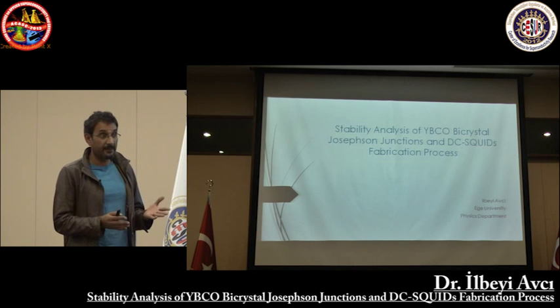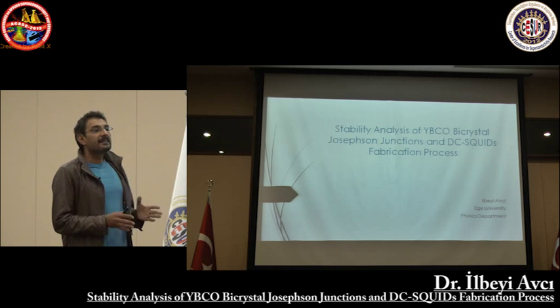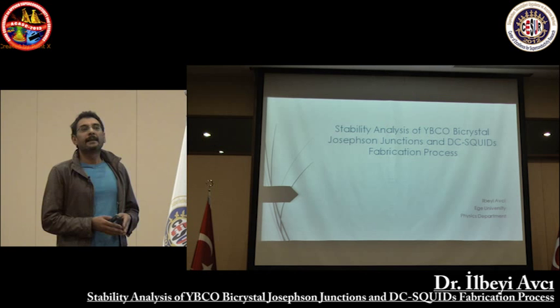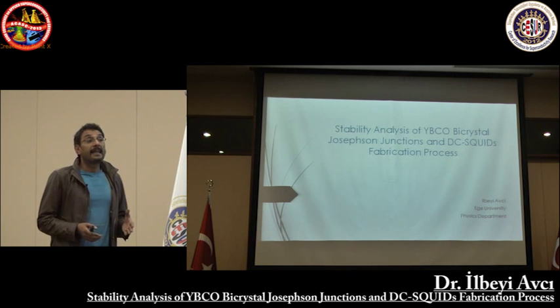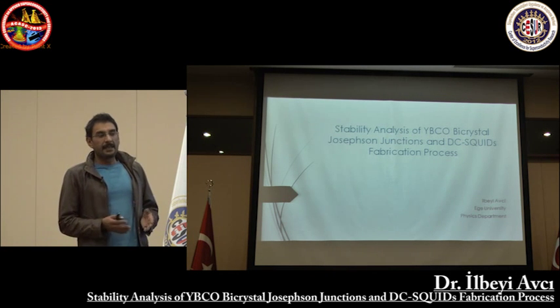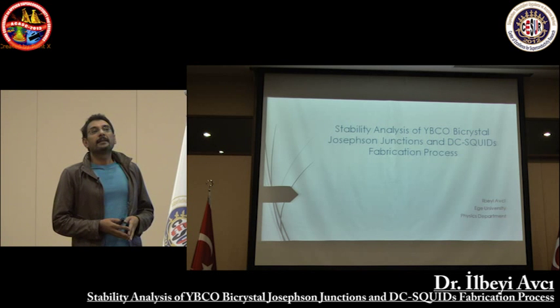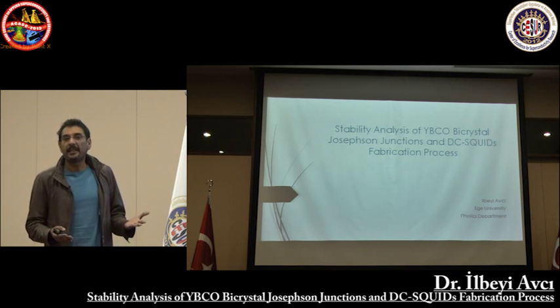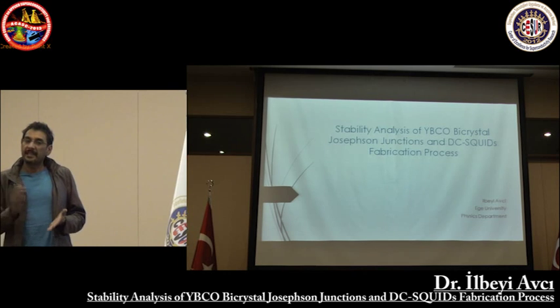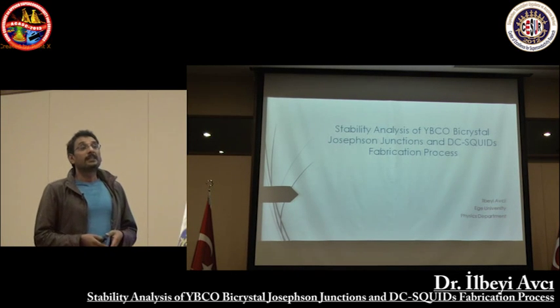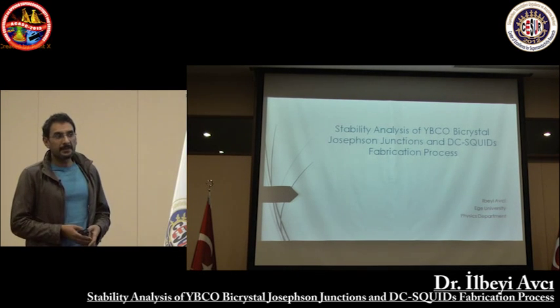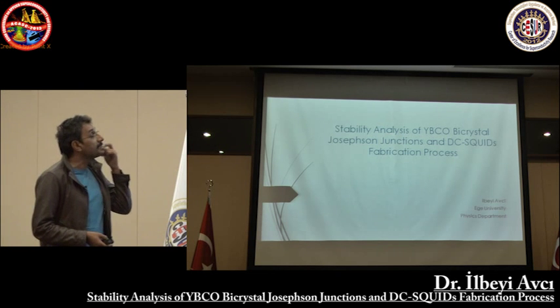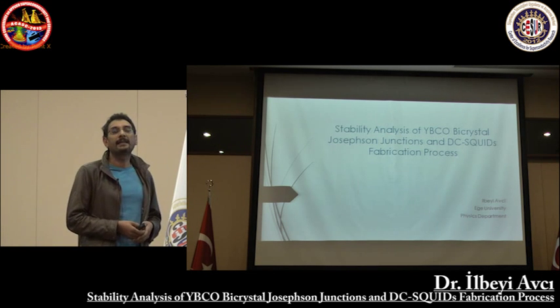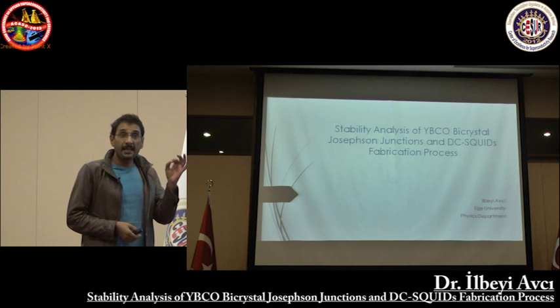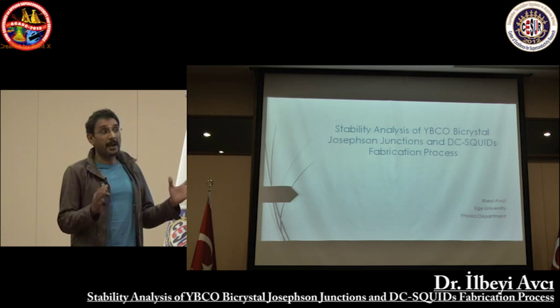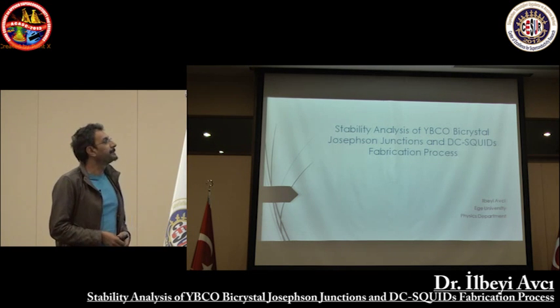As you know, the YBCO thin film itself and any type of devices made by the YBCO thin films are not stable, and they are not reliable in time. After every thermal cycle, they lose their superconducting properties, and that's why there is still no reliable or reproducible parameter set established so far.